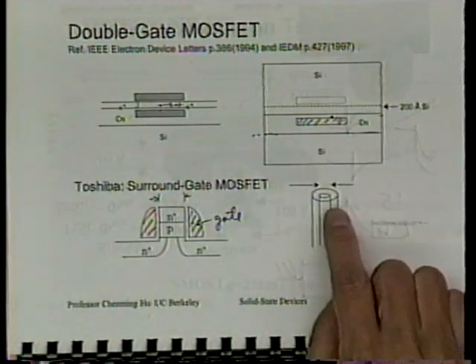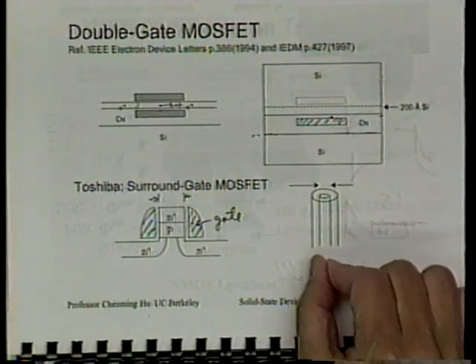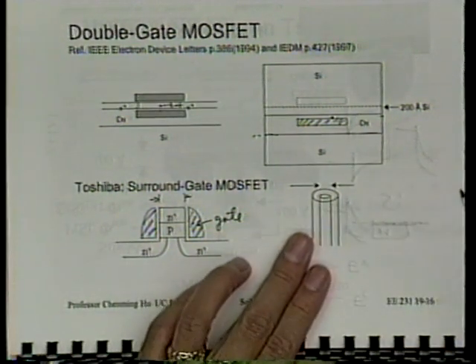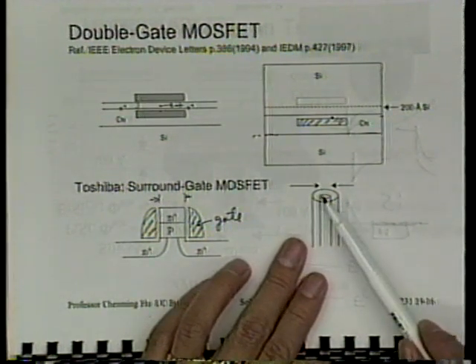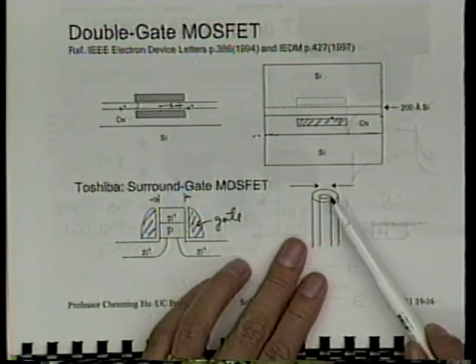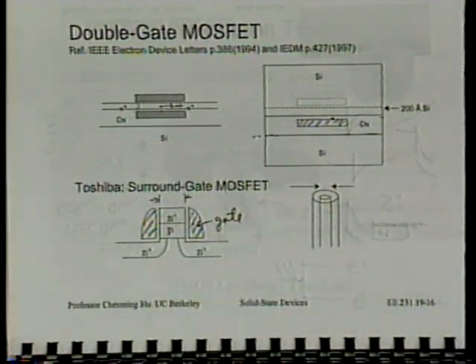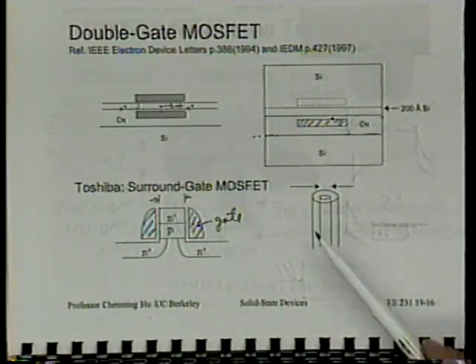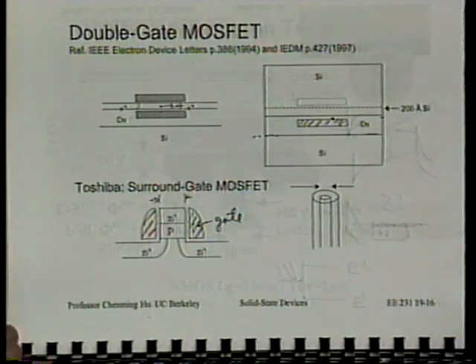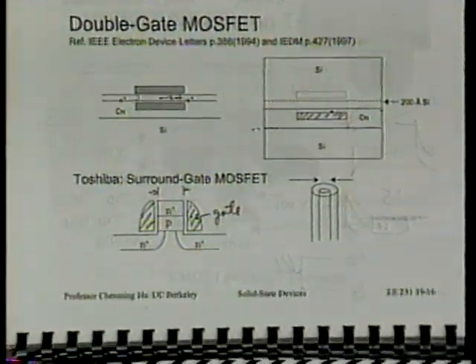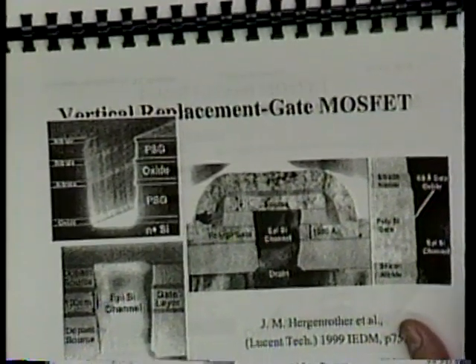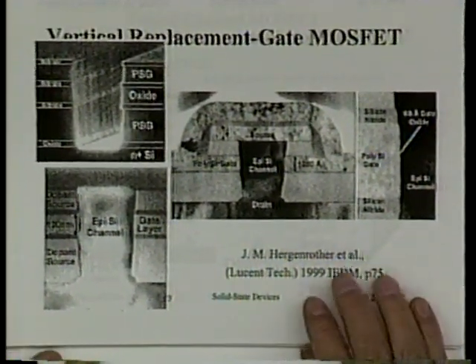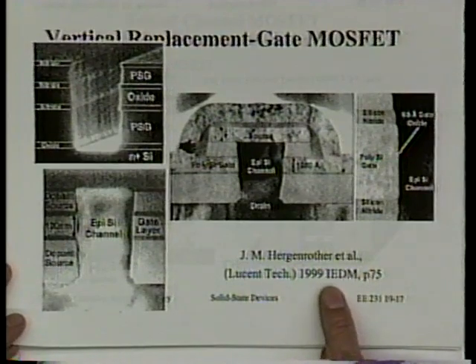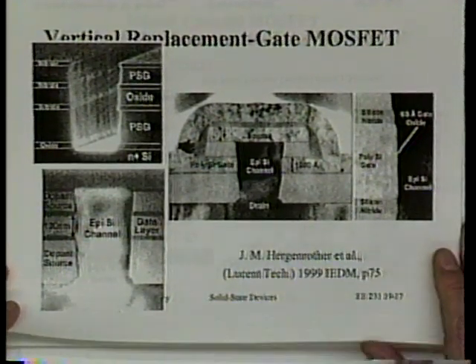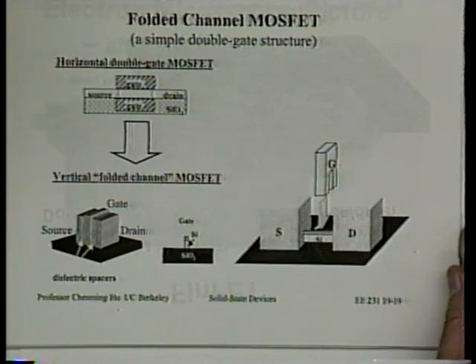Okay? And the variation of that would be actually to make this a small cylinder, etch a small cylinder out of it. In fact, no matter if you use a mask that's a little square, after you do the lithography, you end up with a circle anyway. So you always can etch a small cylinder, right? And maybe you can further reduce the size of the cylinder by oxidizing. And those are the novel ideas, right? Try to do that. Okay? All right. And I will not review some other ideas to give you the reference. This came from Lucent Technology, 1999, IEDM or so. Okay? All right, so what we did, now go back to what we did.